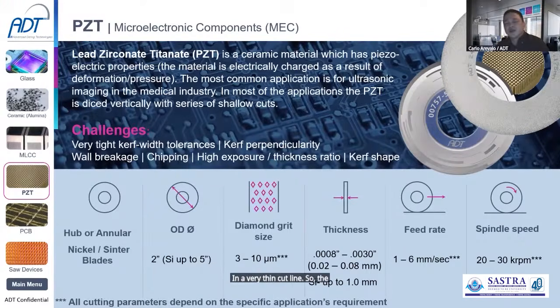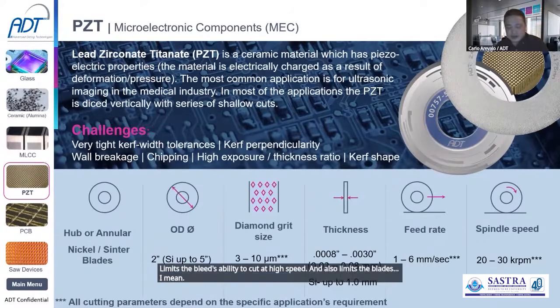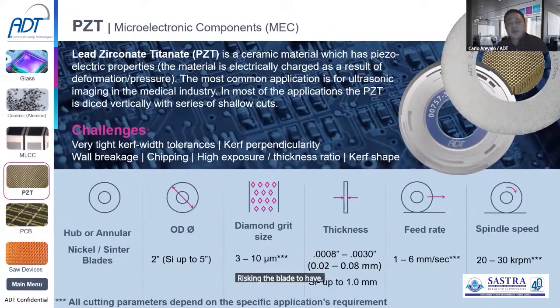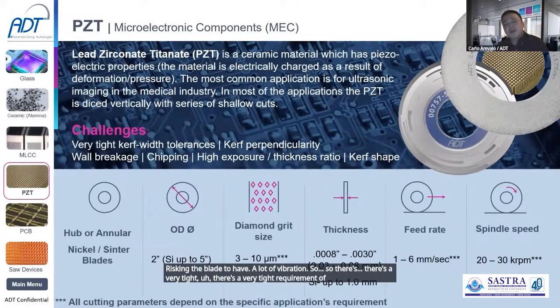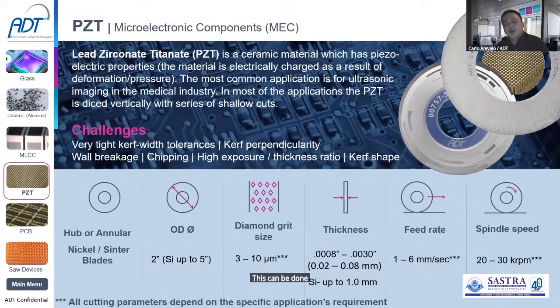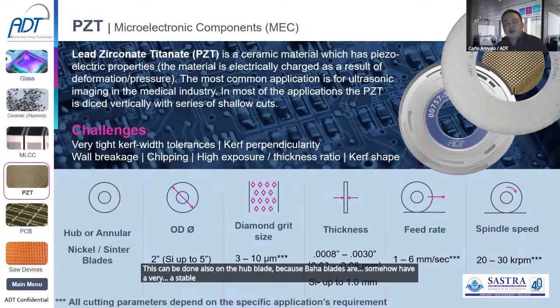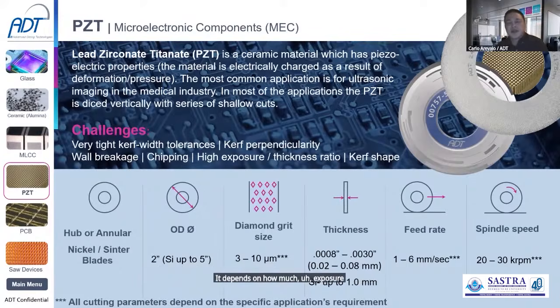The combination of those two parameters limits the blade's ability to cut at high speed, and it also risks the blade having a lot of vibration. So there's a very tight requirement of balancing. If you're doing this application, the blades have to be very well balanced. This can be done also on a hub blade because hub blades have a very stable balance compared to annular blades, but it depends on how much length is needed for the blade exposure. Then you can do it with the annular blade. You can also do this with the hub blade.